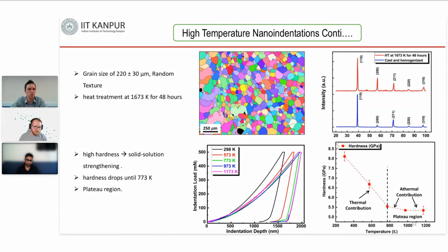Much more accurate compared to any standard mechanical stage, and that means we can target indents in these different phases very precisely, and therefore independently measure these different phases. And again, we can do that at high temperature as well. There was a paper published, I think last year or a couple of years ago, by NPL. They used our system to test individual grains of, I think it was a cobalt chrome material. I suggest that will also be in the high temperature application publication of that paper. So if you want more information, you can find that.